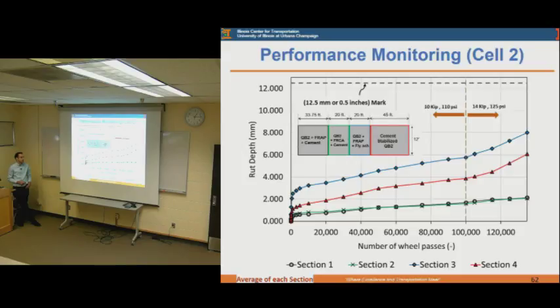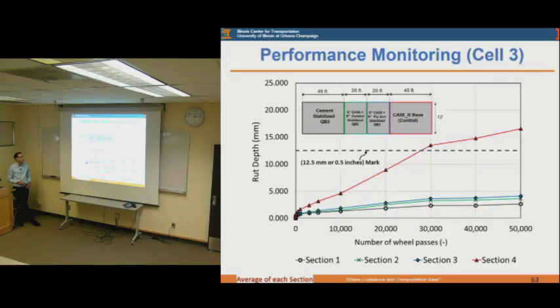But it is this section that has the fly ash, and this section is also, if you remember the LWD deflections and back calculated modulus that I was showing, the one that had the lowest out of all of them. So even here, the trend is similar to the LWD deflections that were measured at different curing times.